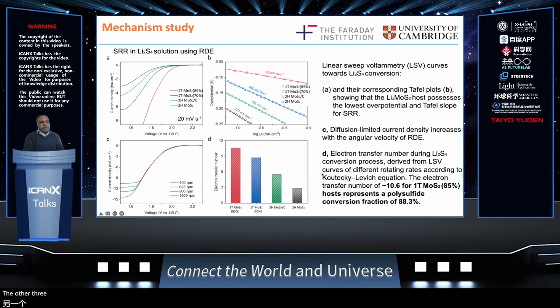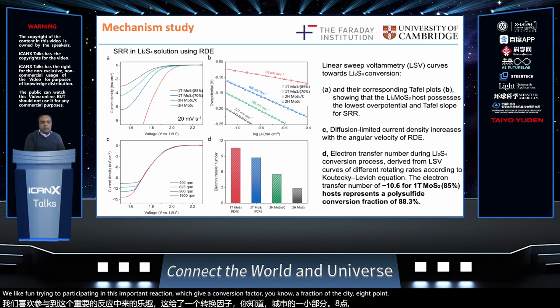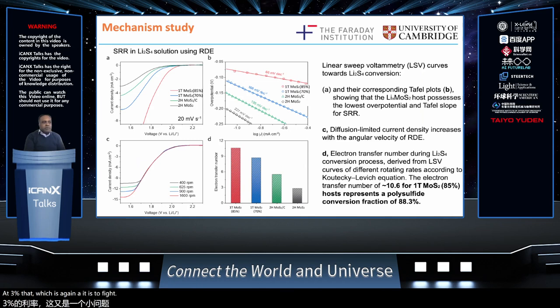So these reactions proceed quite efficiently. The other important point that I wanted to make in this slide was that you can use the Koutecký-Levich equation to extract the number of electrons that are involved in the reaction at 2.1 volt. So the reduction of Li2S4 to Li2S involves 12 electrons, so it's responsible for 75% of the capacity. And with our 1T MoS2, we can, through our analysis, show that we have around 10.6 electrons participating in this important reaction, which gives a conversion fraction of 88.3%, which is quite significant and is responsible for the very high capacity that we see in our coin cells.